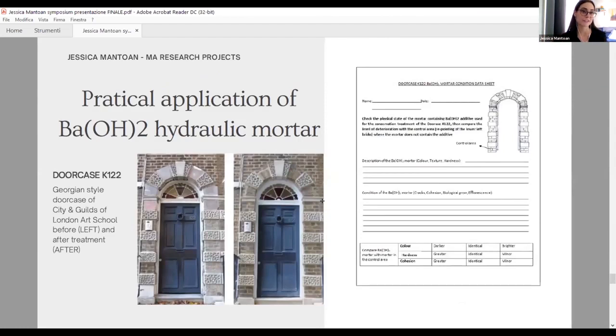After all the scientific experimentation, I decided to use one of the barium hydroxide mortars, in particular a hydraulic mortar containing a small quantity of barium hydroxide, in a real conservation treatment. I used it for the restoration of one of the door cases of City and Guilds of London Art School. And that is a picture of before and after treatment.